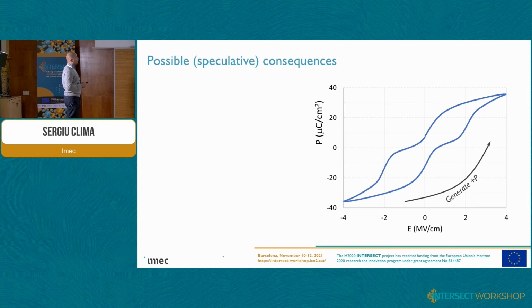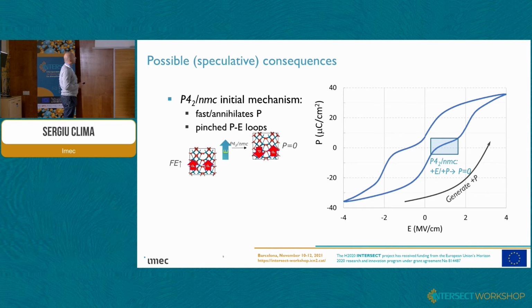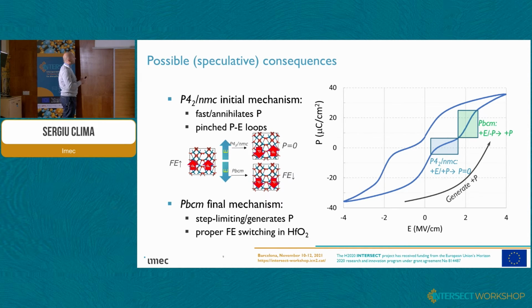So this could well happen in the material as well. However, in this experiment, we see that it annihilated the polarization. Well, and then we can give freedom to our imagination, and we can speculate that this could be one of the mechanisms for interpreting the pinched loops and the wake-up mechanism. So, for example, if we say that first we have this tetragonal mechanism, and then afterwards the other mechanism, then we could, in principle, explain one possible mechanism to explain these pinched loops and the wake-up mechanism, that in the end will get only one mechanism active.